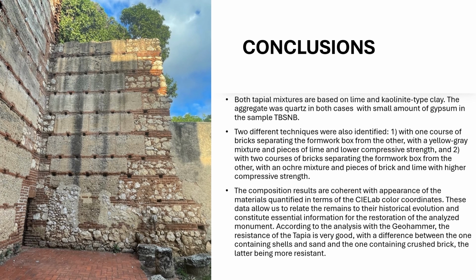The composition results are coherent with the appearance of the materials quantified in terms of the CIELAB color coordinates. These data allowed us to relate the remains to their historical evolution and constitute essential information for the restoration of the analyzed monuments. According to the analysis with the geohammer, the resistance of the tapia is very good, with a difference between the one containing shells and sand and the one containing crushed bricks, the latter being more resistant.